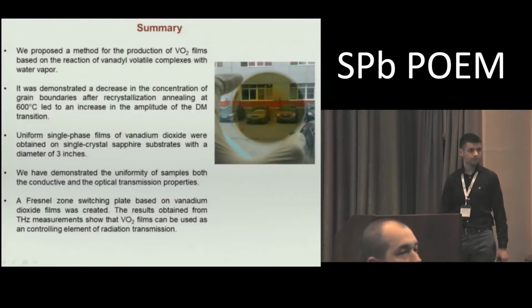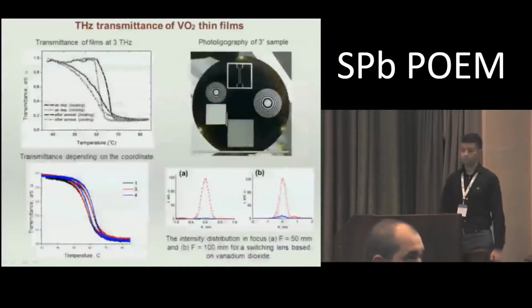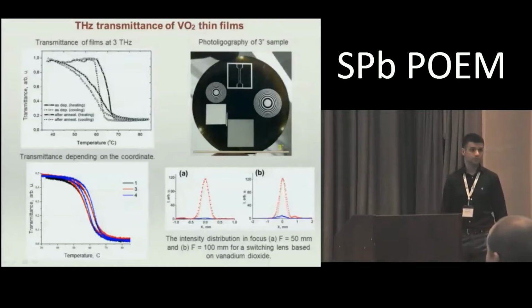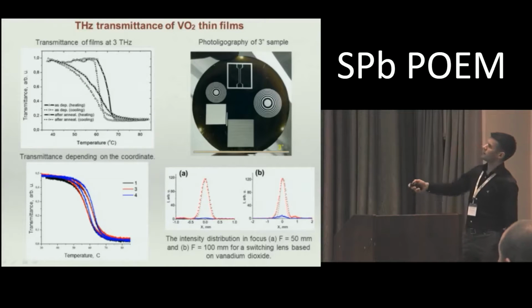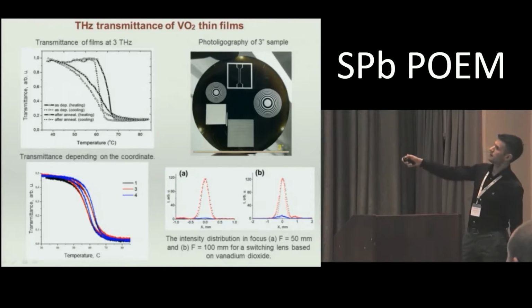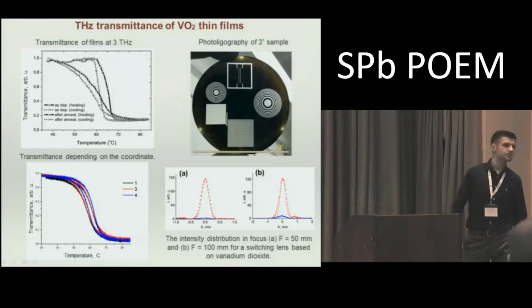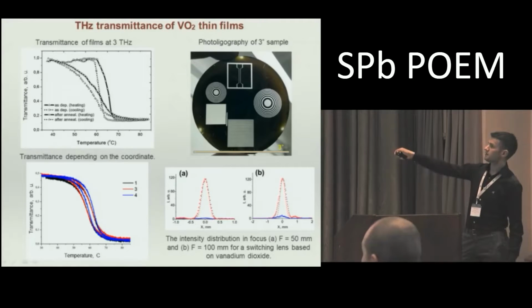Thank you for the presentation. May you go back to the previous slide and look at the first figure? Which curves depict the results after annealing, and which depict as-deposited, because they look the same? There's the same color, yeah. This white hysteresis is for the sample that was obtained without annealing, and here we see the hysteresis after annealing.